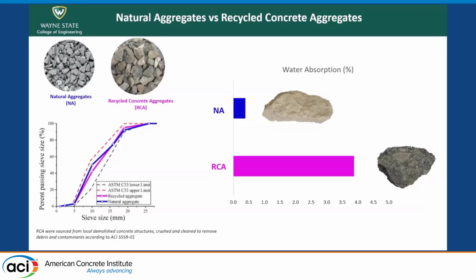The problem that we noticed, and it's usual with recycled concrete aggregates, is that they have almost one order of magnitude higher water percent absorption. That is due to their porosity, which is in the attached mortar around the natural aggregates. And that creates problems when we try to introduce those recycled concrete aggregates into the new concrete.